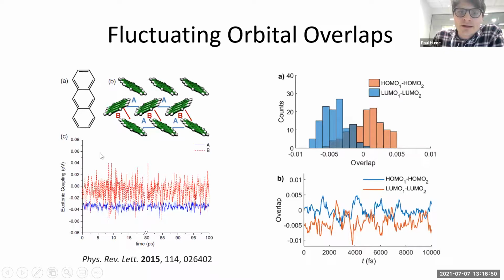And we weren't able to exactly replicate that for IDIC because the molecule is so big. But what we could do is calculate time-dependent molecular orbital overlap fluctuations. I won't go into the details of that because it's pretty dry, but basically you can get an estimate for the disorder associated with your electronic couplings. And the take-home message is that the fluctuations are quite large, but the mean overlap is quite small. And so what that works out to is that the disorder, the fluctuation in the coupling due to short range interactions, is pretty negligible. It's less than 10% or something like that.